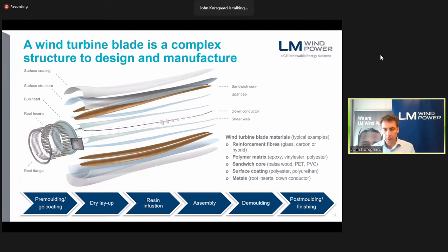Then after that we come to assembly. When the resin has been infused into the dry fabric and the laminate has been cured, then the vacuum foil is removed and the surfaces are prepared for gluing in the webs and the assembly of all the parts. Then we have curing again, and then we come to demolding.